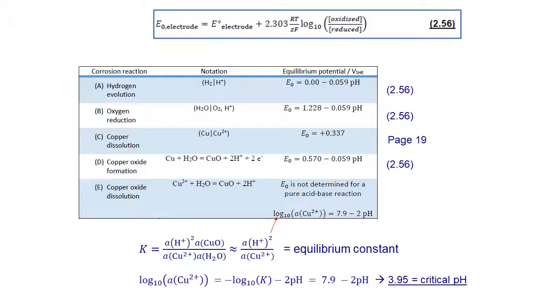We're just considering the reactions of copper metal, copper 2+ ions, so I'm ignoring other possible copper ions in solution, and I'm considering the copper 2 oxide, or CuO. And so what we want to do is predict which of those things will be the stable phase, and to do that we look at the possible reactions between them.